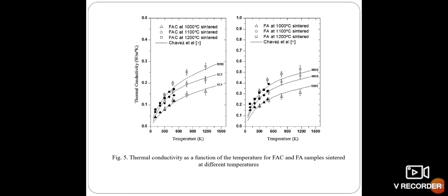The minimum thermal conductivity values at 1200 Kelvin are approximately 0.17 watts per meter Kelvin and 0.32 watts per meter Kelvin for FAC and FA samples sintered at 1000 degrees centigrade respectively. These values are relatively lower than the values reported for the highly disordered oxides such as fused silica and yttria stabilized zirconia, that is YSZ, which are currently the main materials used as thermal barrier coatings nowadays.